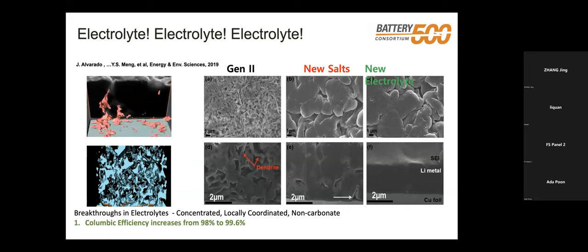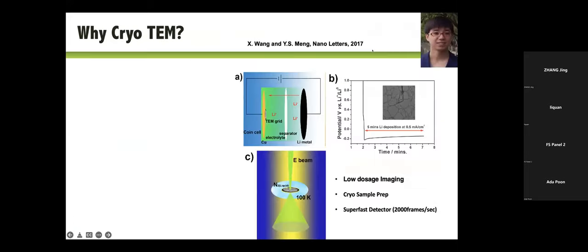So the first big jump of Battery 500 consortium is really changing the entire electrolyte, including solvent and the salts, to the kind of what we call the localized high concentrated electrolyte. And this move is extremely important, because without this, we will not be able to make lithium metal batteries cycle more than a few hundred cycles.